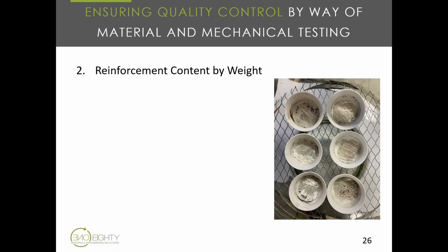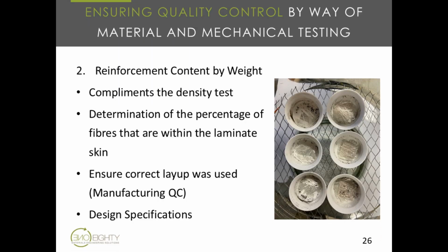So reinforcement content by weight is a test that complements the density tests. It's done for a similar purpose. The test determines the percentage of fibers that are within the laminate skin. So it consists of burning off the resin in the laminate until you are left with only the fibers.